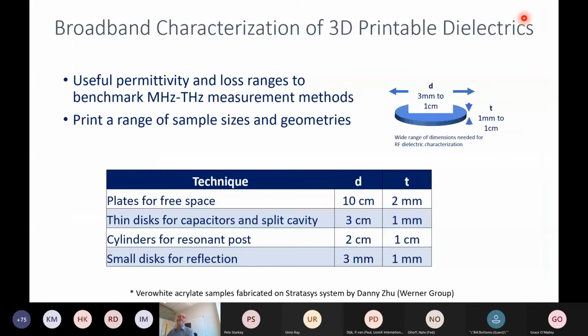And one thing we try to do is take a common material. As we're trying to understand the relationship between these different measurement techniques, it's really useful to have a material that you can print into a variety of different geometries. So then you can put these samples into the different measurements. We need plates for free space. So that would be something on the order of 10 centimeters square, maybe 2 millimeters thick.